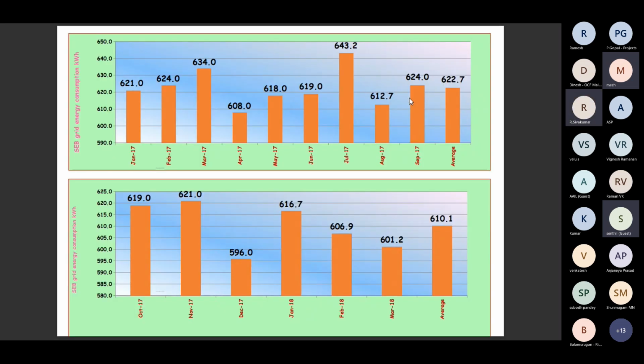Here the energy consumption is reduced, based on the data. On average they took 622.7 units per ton in the earlier stage. With this new raw material charging sequence pattern, they reduced it to 610. Average is 610, from some of the basic heats we took. So almost 10 to 12 units per ton can be reduced by the charge sequence itself. Next one.